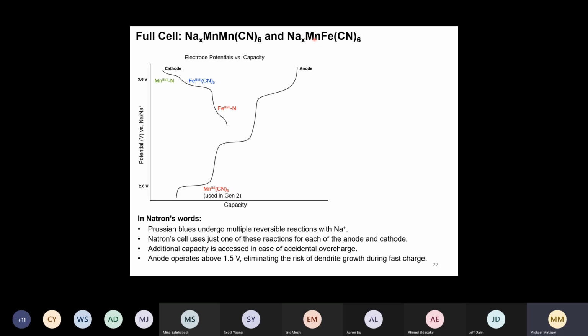You might remember it was written in a little bit of a different way, where you had actually 80% manganese here and 20% iron that was coordinated to the nitrogen. It would be better to write it this way. Sorry, I should have written it this way. And then you have iron, which is coordinated to the carbon. So this 20% iron, which is coordinated to nitrogen, can also be redox active, but they only use the Fe, which is coordinated to carbon. And then the anode has multiple redox couples, as you can see here.